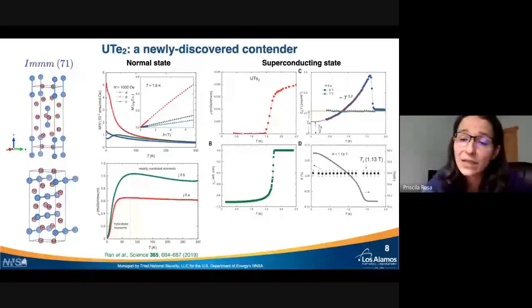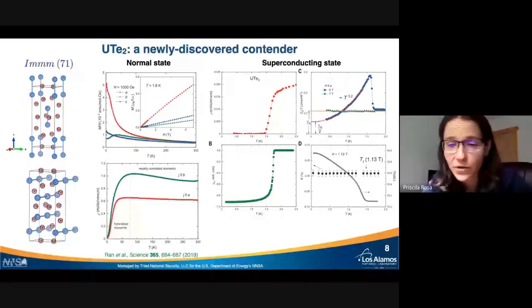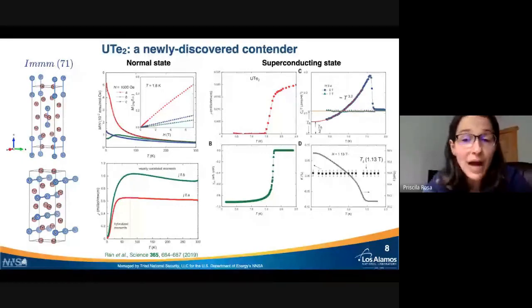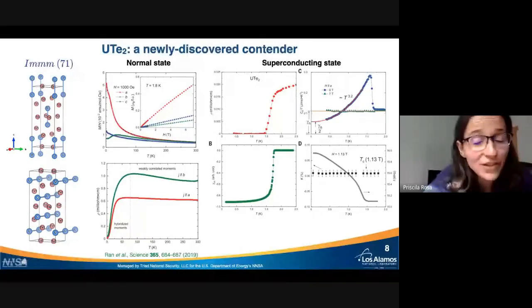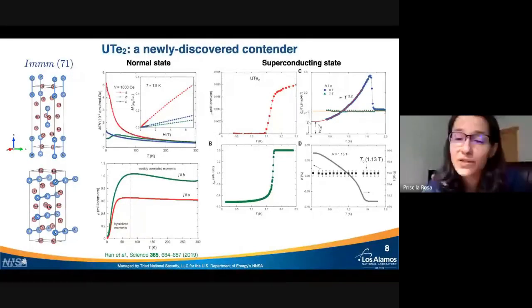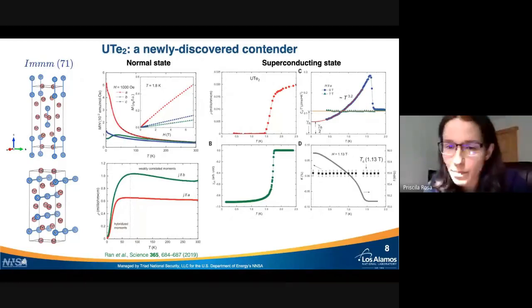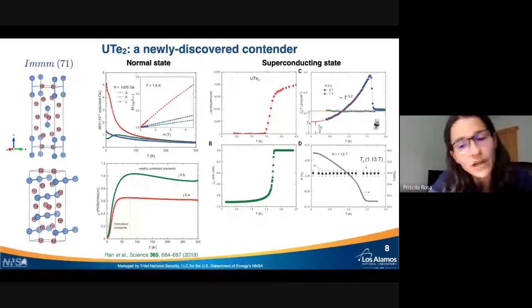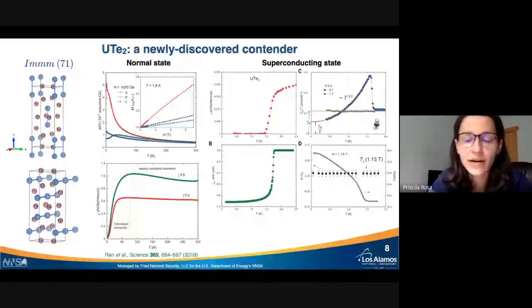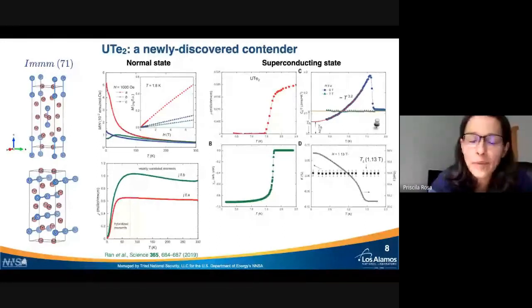So below TC, we don't have an exponential behavior as we would expect from a BCS superconductor. We actually have a power law behavior, and the gamma value, which is the Sommerfeld coefficient, actually does not go to 0, which is also surprising. So I'll put a pin on this because we also don't know exactly what's going on there so far.